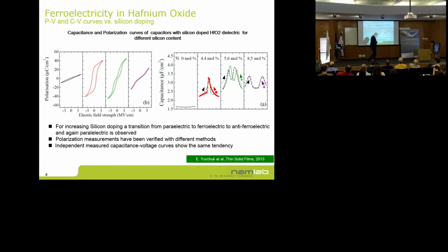So why do I still talk about ferroelectric memories? I could stop now and say it's very good for niche applications, but it will not go anywhere. The reason is, in 2007, a PhD student at Qimonda did some experiments to try to increase the K value of hafnium oxide. And he did something that was very popular at that time. He put different dopants in there to stabilize higher-K phases. For instance, he worked with silicon.